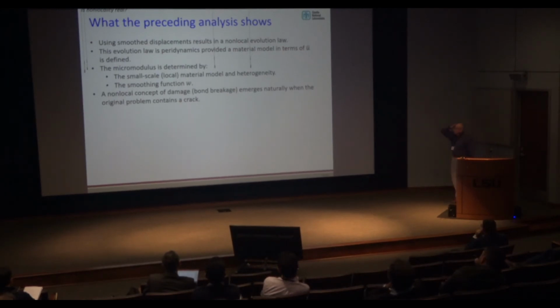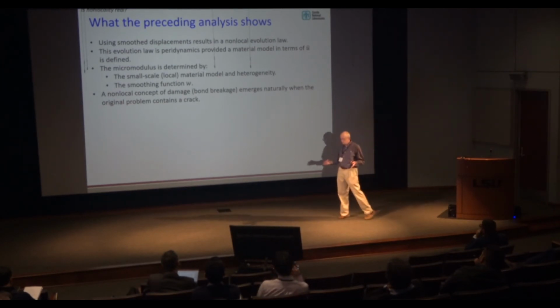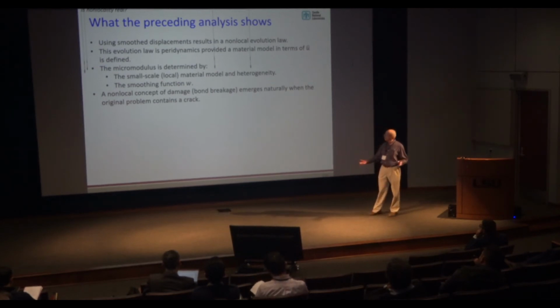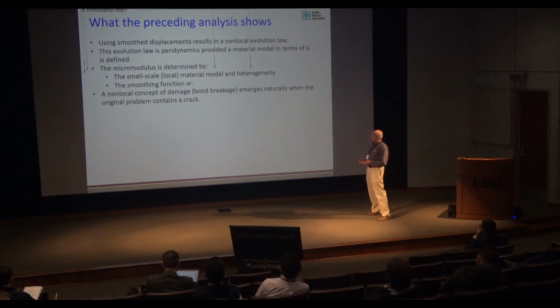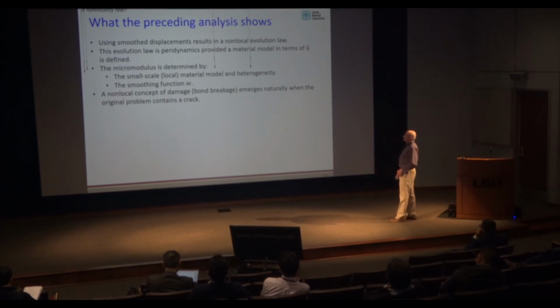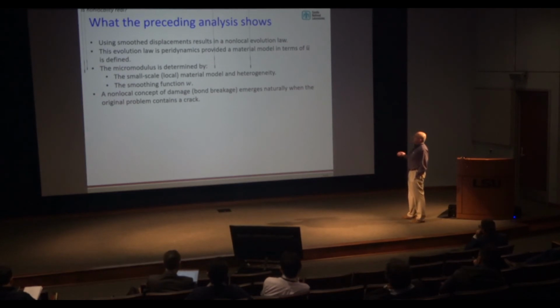So to summarize so far, what this shows is that when we work with smoothed degrees of freedom, we end up with a non-local linear momentum balance. And in this case, I showed that non-locality can be put in the form of the peridynamic equation of motion. The micromodulus, which is the material model for the smooth degrees of freedom, can be derived from the small scale material properties, but it always involves the smoothing function. So if you choose a different W, you'd end up with a different micromodulus.